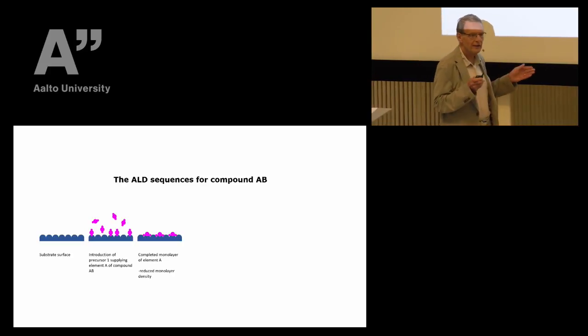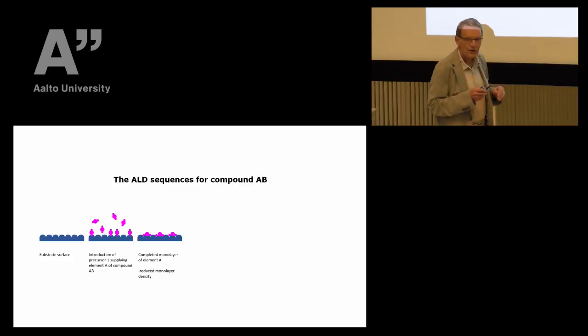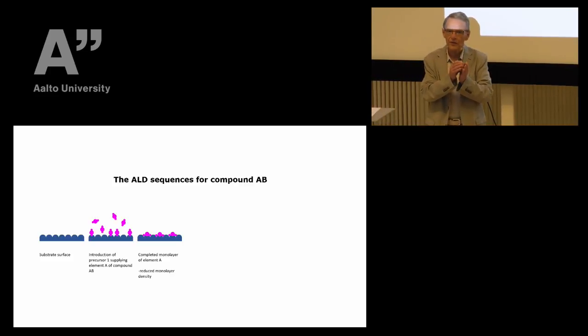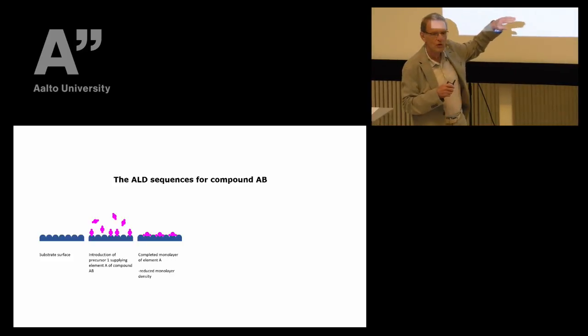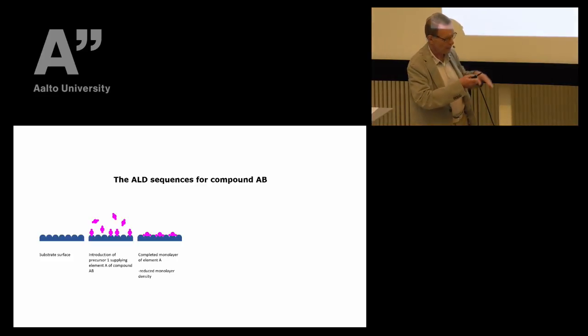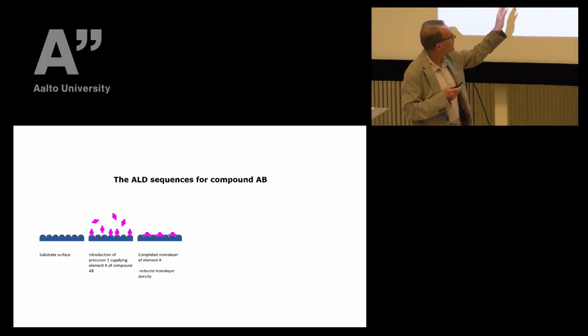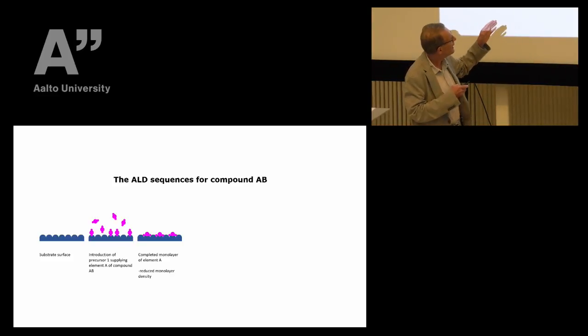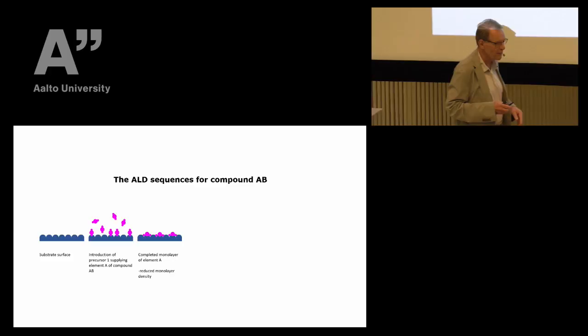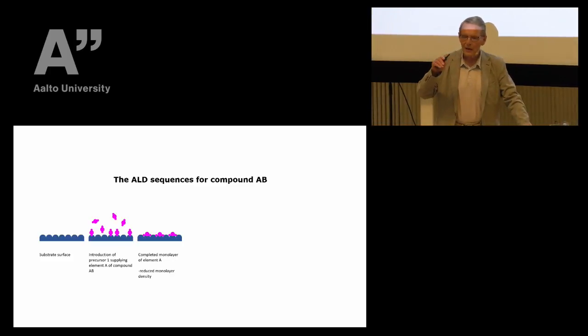Nature doesn't work that simply, indeed. So a surface makes a discontinuation of the bulk, which means that in the bulk the individual atoms are coordinated in all directions. On a surface they have to coordinate on the surface only, which means that in that step the individual atom occupies more than the space of a final atom. And that's why that was my first problem. When we started working with it, I was expecting to have a full monolayer in a reaction cycle. And I was very disappointed that it doesn't occur.